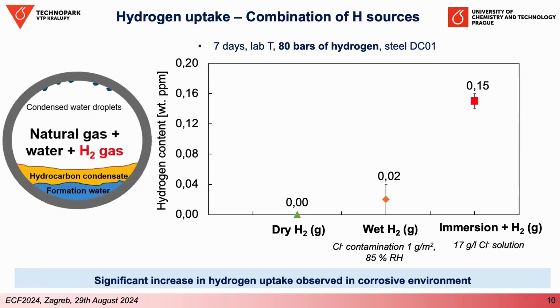But if we combine the gaseous hydrogen with other sources, with a corrosive environment, we can see a significant increase in hydrogen entry, and it's most pronounced when the steel is in direct contact with the water and in high pressurized hydrogen. We used here just a plain model of formation water with the same level of chlorides as is usual in the formation water, and saw this result. So we were curious